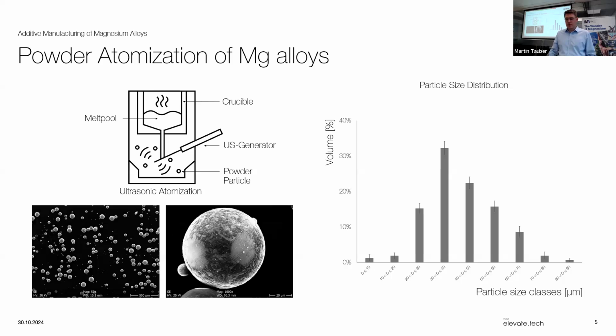Because for the medical applications, especially since magnesium is a degradable alloy, we need really high purities. And for that reason, we do the powder atomization in-house ourselves. So on the top-hand side on the sketch, you can see how the powder atomization is being done. It's basically a melt pool, and the molten material is falling on an ultrasonic generator, which is then vibrating, and the particles with the grain size that we need are being formed.